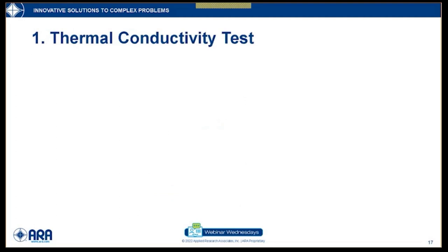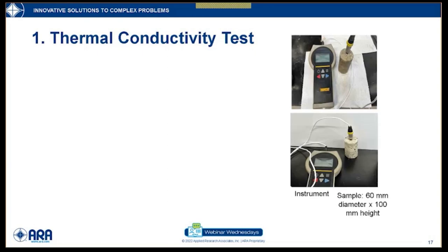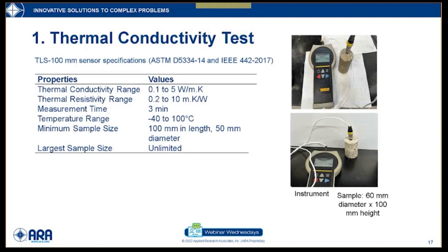To determine the thermal property of the soil, whether the soil is high thermal conductive or low thermal conductive, before and after the cement plastic stabilization, the thermal conductivity test was performed. This figure shows the TLS 100 millimeter sensor equipment. It has a 4-inch long copper probe, which can heat and cool, and this probe has to be inserted fully into the soil sample, and after a certain amount of time, this equipment gives the thermal conductivity of the soil sample.